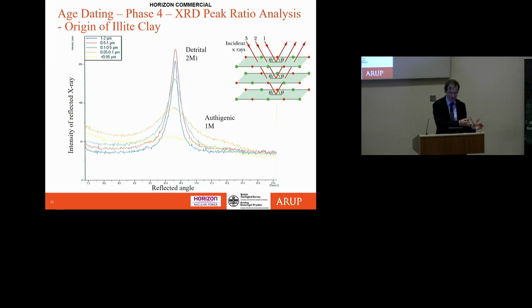So then, not only do we do it by scanning electron microscope or scanning transmission electron microscope, we then go and we say, okay, what's an alternative method that would be independently verifying the origin and provenance of these clays? And quite widely used in other parts of geoscience is using the X-ray diffraction peak ratio method to look at the crystal structure. And when you're doing X-ray diffraction, many of you will know you're shooting down the X-rays and they bounce off the lattice of the crystal.